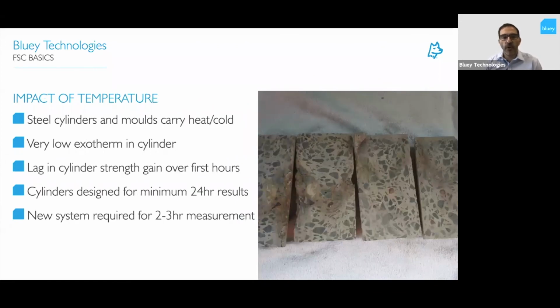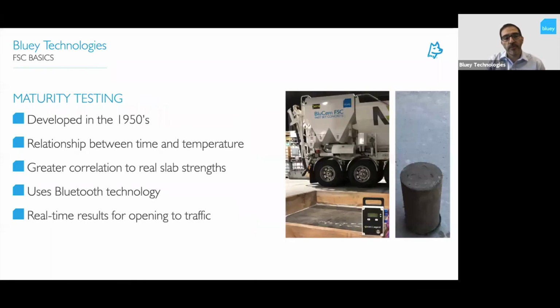The cylinders have low exotherm. They actually hold a lot of the cool. They don't allow the concrete to generate its natural heat, which means there's a lag in cylinder strength over the first few hours. So the cylinders aren't truly representative of what's happening in the slab. Cylinders are old technology, and that's why we needed this newer system for 2 to 3 hour measurement, which is our maturity testing. And again, we'll talk about this in the maturity testing presentation.